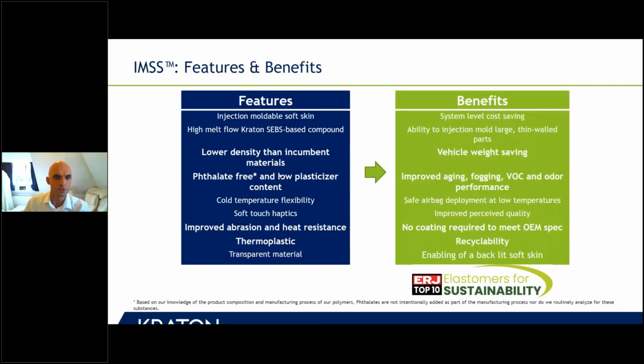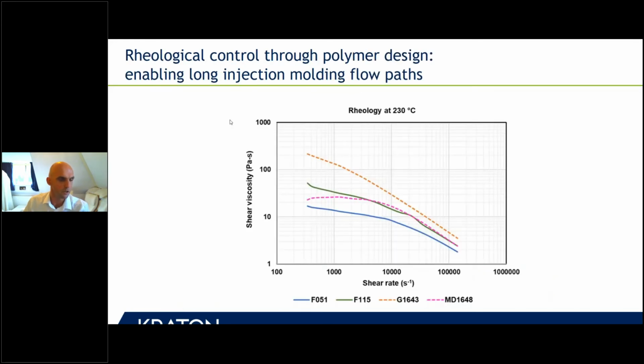And in the end, the result is basically, and I'm looking at sustainability here, we actually got nominated for an ERJ top 10 award. And actually, the outcome is that you can save weight on your vehicle. There's improved aging and fogging and VOC and odor performance because it's phthalate-free and low plasticizer. In some cases, we reached an improved abrasion and heat resistance, and it's thermoplastic, which is of course helping recyclability. Now, of course, you're curious about the technology behind this, and the technology is all in rheology, and we contribute part of this, and our compounding customers